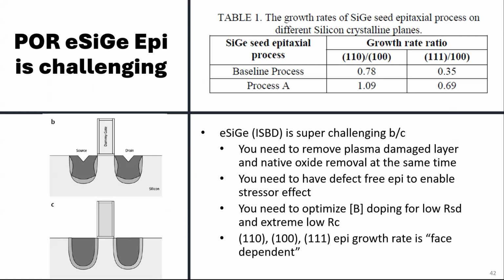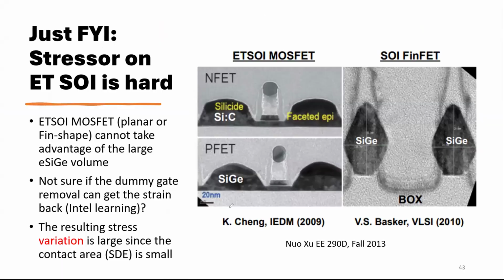Let's look at IBM. It looked nice though. They did a growth from here, right? And they have to grow it thicker. This is called the raised source drain. They raise it, right? But remember, this is only very thin. They are only less than, say, about 6-7 nanometer. So you start on a very thin layer and you want to do epi.